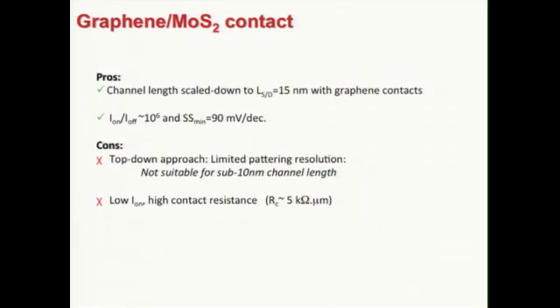But there are two issues that need to be solved before continuing. The first one is that, well, still we are using a top-down approach. We are using lithography so that the resolution is limited. Well, the device is about 15 nanometer, and our pattern is about 10 to 12 nanometer. But obviously, we cannot go below 10 nanometer using this technique. So we need a more bottom-up approach, something with nanometer resolution, single-digit resolution.